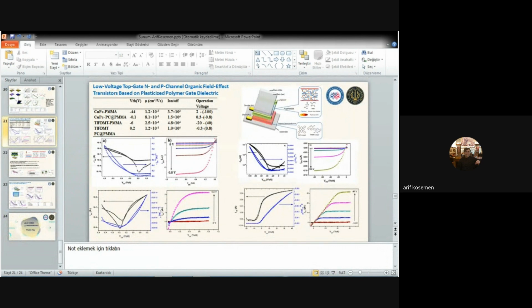And this is another approach for the gel-like dielectric material. We used again the polymethyl methacrylate and propylene carbonate combination to get the gel-like dielectric material. But instead of the P3HT polymer, we used copper phthalocyanine as the active layer in this study. Copper phthalocyanine is a small molecule, and we evaporate this molecule onto the source drain electrodes. And in this study, we used interdigitated electrodes. And this is our device structure.